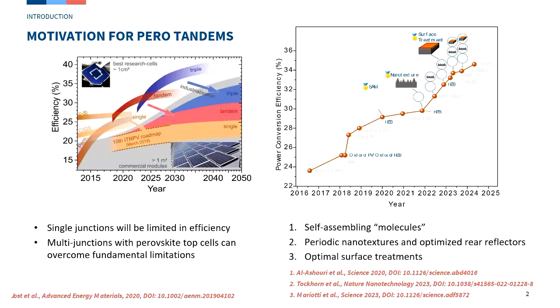And last but not least, this one here, 32.5%. What we did there is we did a surface treatment, a so-called passivation of the perovskite surface, in order to get a better film, or less recombination at that contact, and with that we could have a very high open circuit voltage, which is still among the best today. All right, so that's efficiency, but of course we understood from yesterday, and we know in the community, that